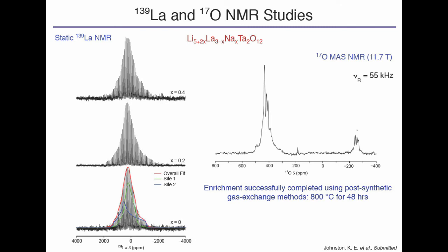Again, we can try and look at this indirectly using oxygen 17. Oxygen 16 is not NMR active, so what we need to do is enrich our samples with oxygen 17 in order to be able to do some oxygen experiments. And this is quite a costly process, so you only do this when you really have to do it. We managed to do this for our garnets, and we exchanged it successfully.